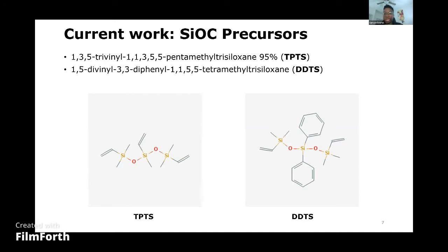As shown in the figure underneath, the main structural variable for these polymeric precursors that have rather comparable structures is in their carbonaceous pendant groups, wherein in DDTS we do see the addition of high molecular weight phenyl groups as opposed to vinyl groups which are present in TPTS oligomers. Essentially, what we sought to do is to identify whether minor changes in the structure of the oligomers result in significant differences in the pyrolysis behavior of the polymeric precursors, as well as the structural evolution of their respective silicon oxycarbide ceramics.